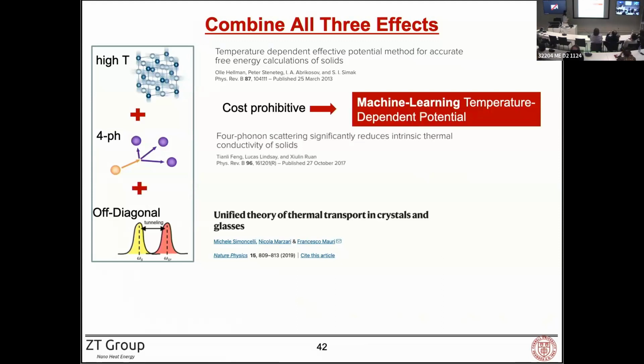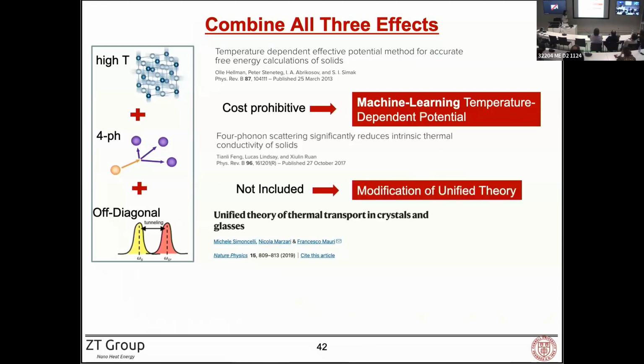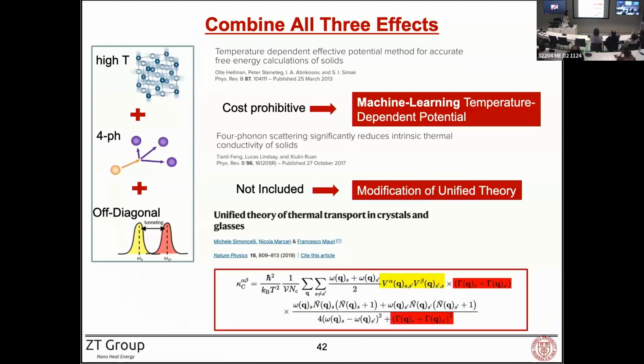Now, to include this four phonon scattering and considering these off-diagonal term contributions, it was not included in the original unified theory framework. So we need to modify the unified theory to include the four phonon scattering. So that's basically we included those scattering terms for the four phonon scattering. And another contribution we made was to make this unified theory compatible with the frozen phonon framework.